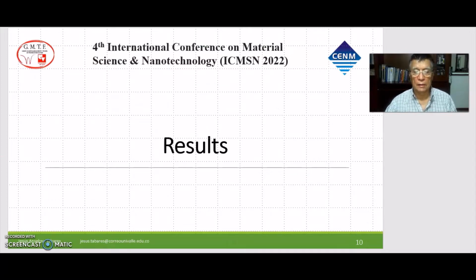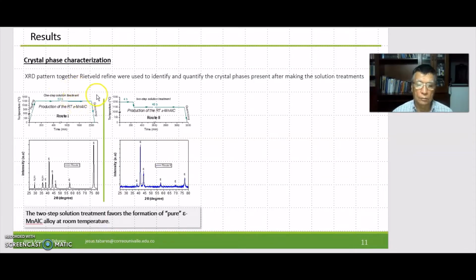Now I will pass to present the main results of this work. Here I show the X-ray diffractograms of the resulting manganese aluminum carbon alloy after following two different solution treatment routes. When we followed route 1, the resulting manganese aluminum carbon alloy is a solid heterogeneous mixture that has three different phases: epsilon phase, which is the majority phase, together with an aluminum-rich phase and a small amount of tau phase.